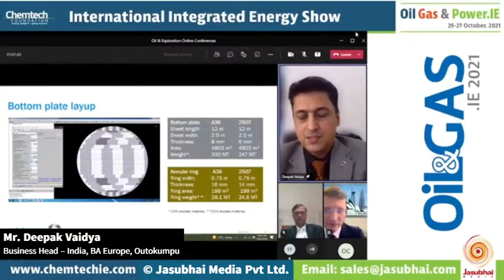In A36, the thickness being used is 8 mm, but where you use super duplex stainless steel, the mechanical strength, RP 0.2 value, is almost double, so you have a possibility to reduce the thickness. Of course, you cannot go down from what is recommended in the standard, so we took just 6 mm. Then we calculated the area of the tank, basically the bottom plate.